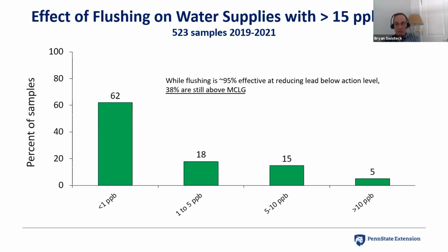Above the goal of 0 parts per billion. So that's a particular concern if we're dealing with young infants in the home or children in the home, where we really don't want to have any amount of lead at all. Running the sample wasn't enough to get it down below detection. And that's a case where if there are children involved, for sure, we might say, maybe try running it for another minute and let's see if we can get that down even further. Or do we really have to go to something like an RO unit or a carbon filter or something to really remove all of the lead, because we just can't flush enough of it out by just running the water.